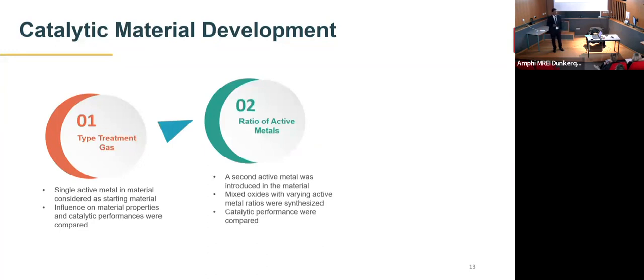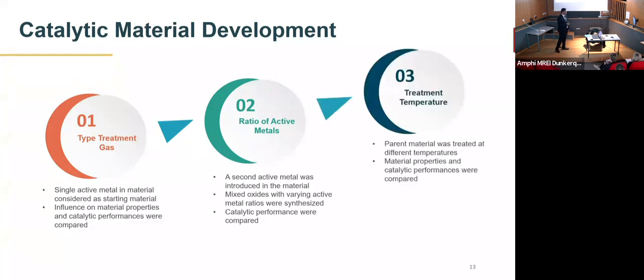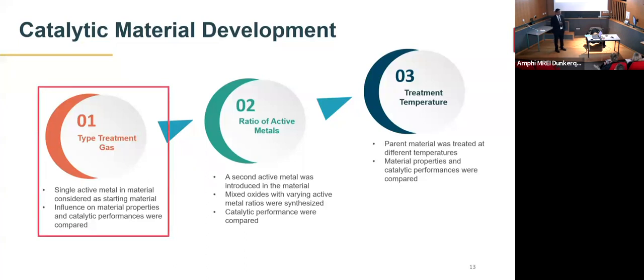In this case, we introduced a new active metal into the material, and we played around with the ratio of this active material and investigated the influence on the catalytic performance. And finally, we optimized the treatment temperature. So we treated the parent material at different temperatures, and for the catalytically active component that we got at the end, we compared its catalytic activity and tried to see the influence of the treatment temperature on the catalytic performance. In this presentation, I will go deeper into this first part of our optimization process, that is the type of the treatment gas.